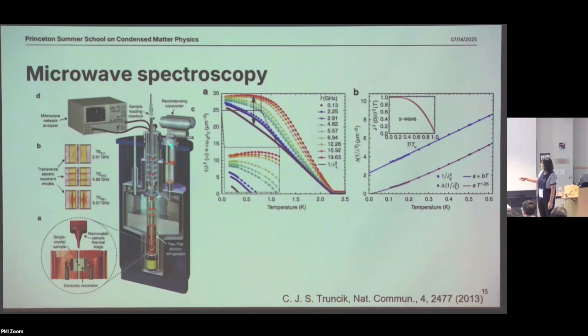As you can see, they hooked up the VNA to send microwave in and to measure the microwave coming out. So that's a type of reflectance measurement. Here they plotted as a function of temperature in the left-hand figure, and the right axis is sigma 2. Sigma 2 here is about the superfluid density again. As a function of temperature, it shows a pretty linear increase when the temperature drops. So it's different from the tin and lead films the previous study was talking about. Here, instead of an exponential increase, it's a linear increase. And this linear increase is directly related to the nodal structure. So they used the microwave study here to prove that this material has a D-wave pairing instead of an S-wave pairing.